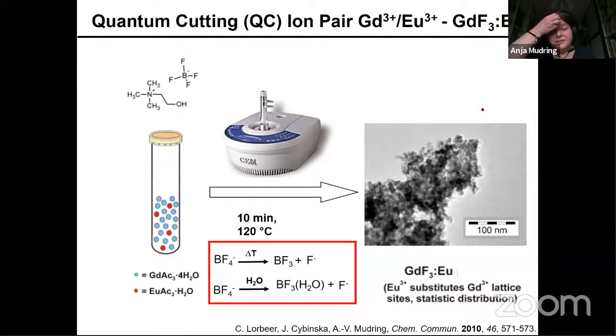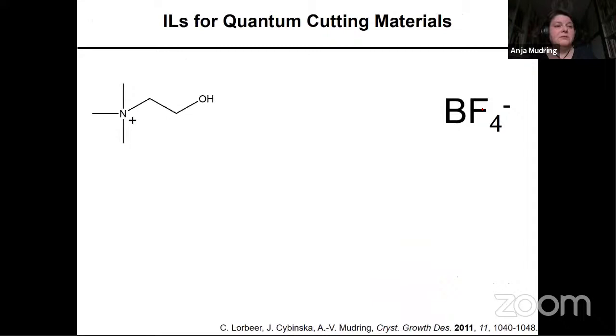The question that I sometimes get is, well, you use BF4 minus ionic liquids. You have to make at least the BF3. Is really your way, when you think in a systems way, better? Well, the BF3 industrially gets made from boron oxide, and you treat calcium fluoride with sulfuric acid. It's still not a green synthesis, it never will be, but it's a lot better than treating anything with HF. So in that context, this reaction is really good and green.